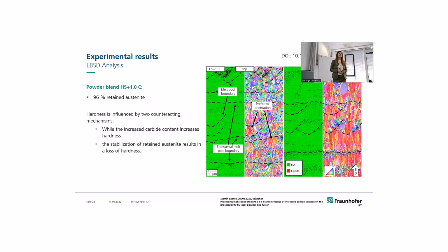When adding 1% carbon, we have a nearly fully retained austenite structure, which is interesting because we're talking about high-speed steel, but we were able to generate a fully austenitic microstructure. And in the paper it's explained a bit more, but we think there are two mechanisms that influence the hardness and also the cracking of high-speed steels. While with increased carbon content, we increase the carbides in our material, obviously, that can increase the hardness. But by stabilizing the matrix with retained austenite, we lower the hardness. So that's the reason why we have a lower hardness by increasing carbon content.